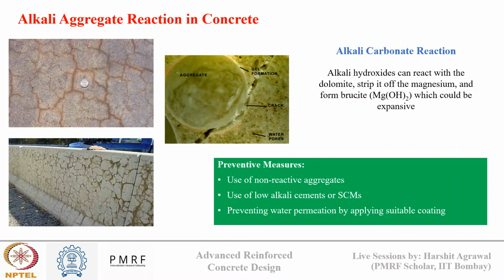So this degradation generally appears in the form of map cracking. You can see, like a map, cracks appear on the surface of concrete. Here and here you can see how cracks are coming. So this is the effect of alkali silica reaction. And you can see in this image how gel formation is occurring at the aggregate surface. So you can see this aggregate and this gel that is present, and this gel is generating cracking.